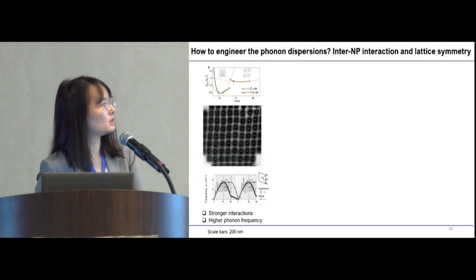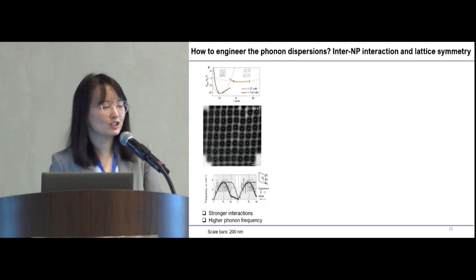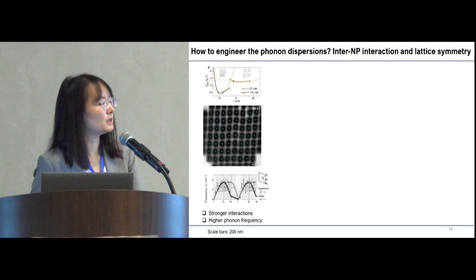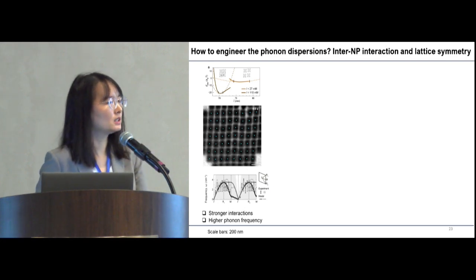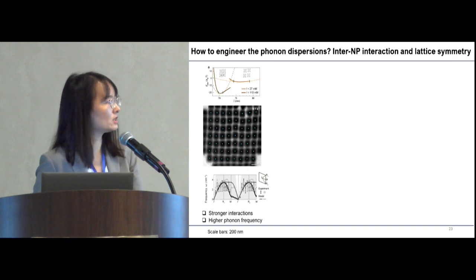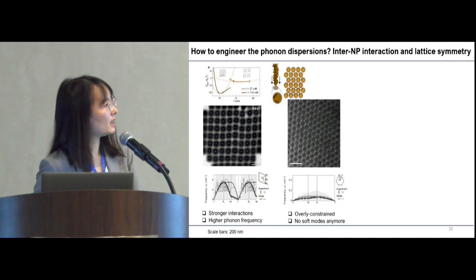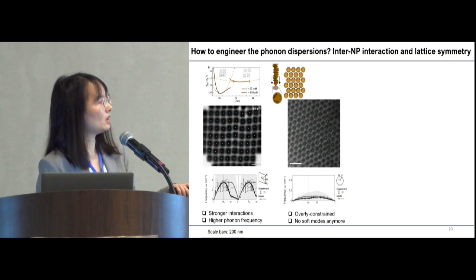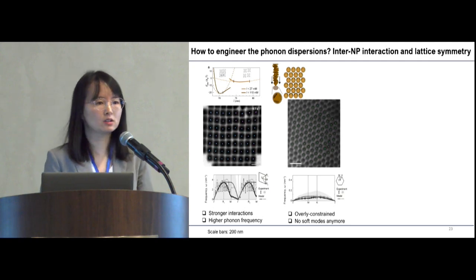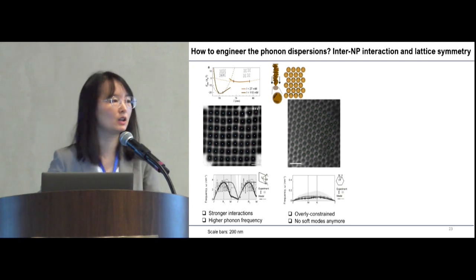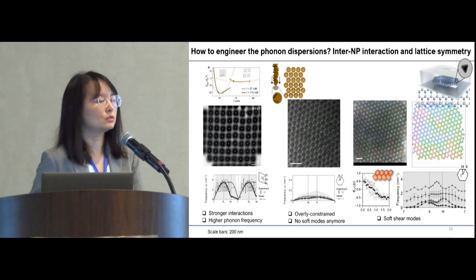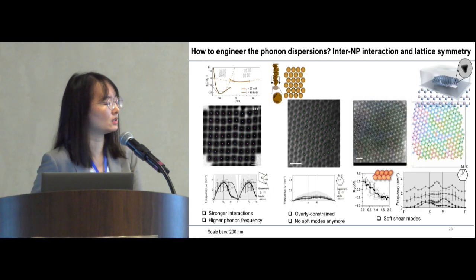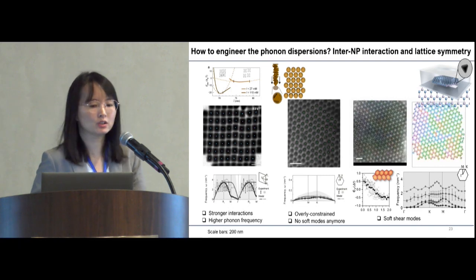And then based on this measurement, we start to ask how to actually engineer the phonon dispersions. Because we have quantitative measurement, we quickly arrive at the conclusion that first, we can change the interparticle interaction, which can increase the phonon frequency. We can also change the lattice symmetry, which can change the topology of the phonon dispersion. For example, in the hexagonal lattice, we no longer have soft modes because now the lattice is overly constrained. We can also go to even more complicated soft lattices shown there with soft shear modes.